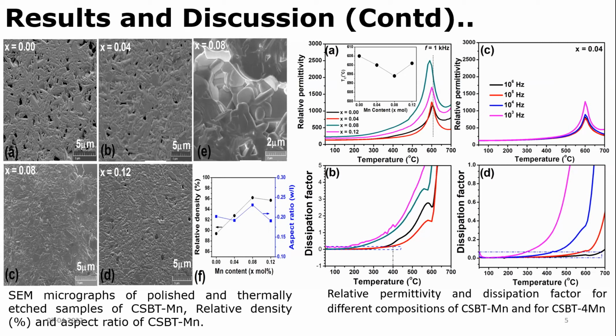Here you can see the value of W upon L, that is thickness upon length, changes notably with the addition of MnO2. This is because MnO2 does not accelerate grain growth, and pores are reduced with the addition, with the increase in the concentration of Mn.